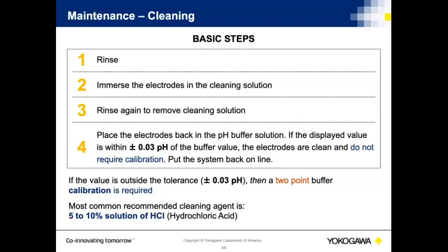Most common cleaning agent, hydrochloric acid. I even go further than this and basically say, use the weakest solution that you can to clean the pH probe. If it just takes water and a soft bristle brush to clean the pH electrode off, just use that. Even decrease your concentration of hydrochloric acid to less than 1%. If that gets the buildup on the pH probes off, fine, you're done.